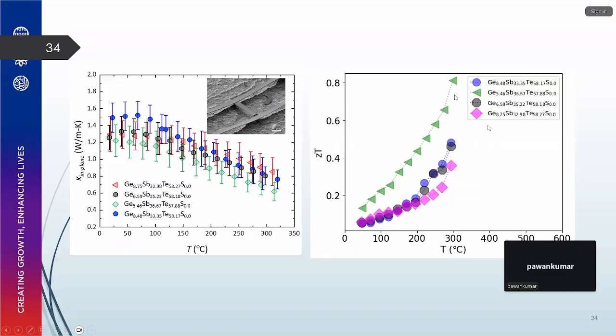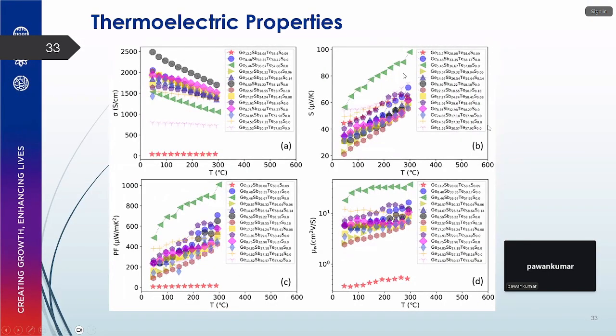But I think it also matters if you can control the doping, because Seebeck is in the 30, 40, 50 range. The maximum rating for this sample is close to 100. I want to reach at least 200 here. Do they have a way of doing that? I think the more interesting thing is if they somehow put more sulfur in germanium telluride, because germanium telluride is metallic here, or introduce some kind of vacancy in germanium so that these numbers can be improved. But I think we don't have any more samples, right? They have standard targets, unless they make the target with different germanium vacancies or extra germanium.